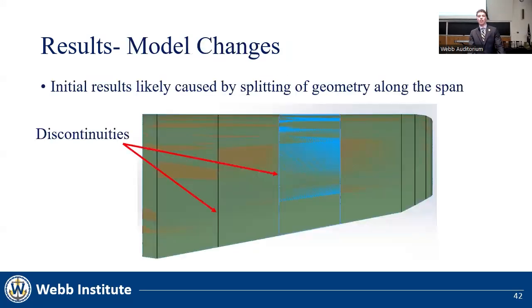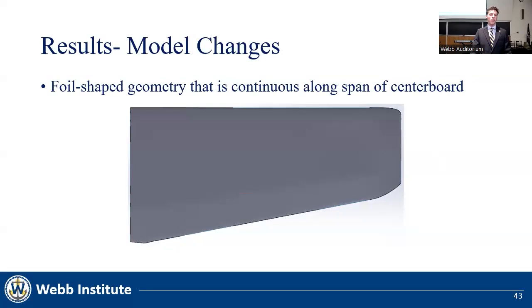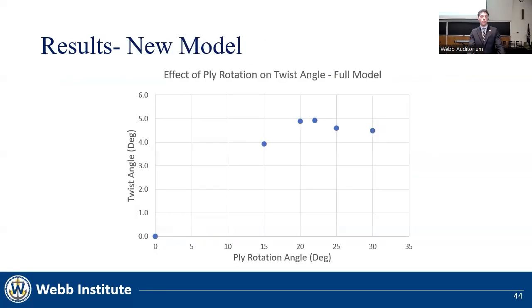We performed further analysis to analyze what went wrong, and we determined that the discrepancy was likely caused by the way we had modeled the centerboard. Initially, the geometry had discontinuities along the span of the centerboard, which we assumed would have been handled properly by the FEA when bonding the mesh. It appears this is not the case. We redid the model with a geometry continuous along the span of the centerboard and got these results. This is for the righting load condition, and as you can see, at a 0 degree ply rotation angle, we have 0 twist, and we achieve a maximum twist in the righting load condition of just under 5 degrees with a 22 degree ply rotation angle.